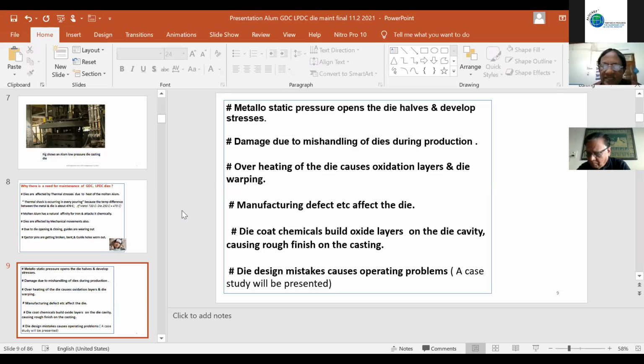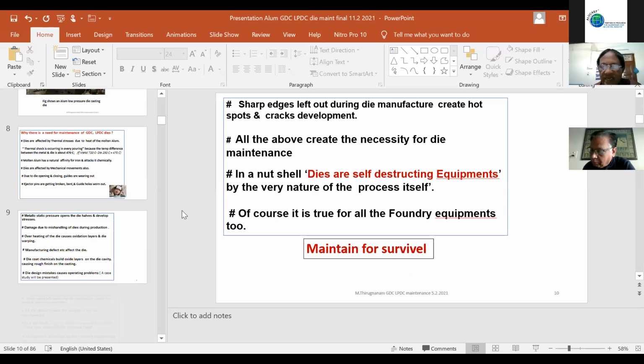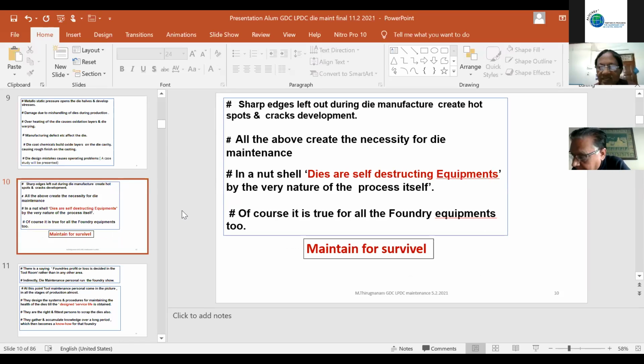Die coat chemicals build oxide layers on the die cavity, causing a rough finish on the casting. Die design mistakes also cause a lot of operating problems. Sharp edges left out during the die manufacture create hot spots and crack developments. All the above create the necessity for die maintenance. In a nutshell, dies are self-destructing equipment by the very nature of the process itself.